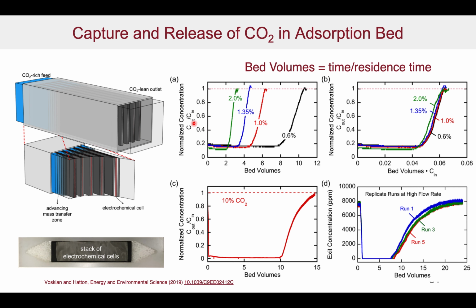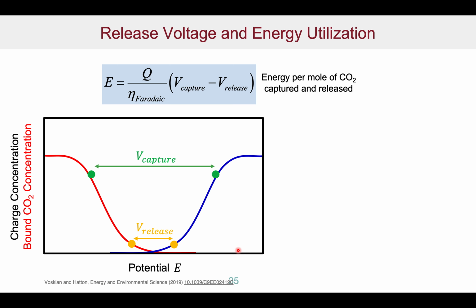You can see here the normalized outlet concentration as a function of the inlet concentration. Let's look at this one here. You can see we're removing essentially all the CO2 in this particular case until about 10 bed volumes, which is the time over the typical residence time. Only then do we begin to see a breakthrough. This shows a very strong adsorption capability for the beds.